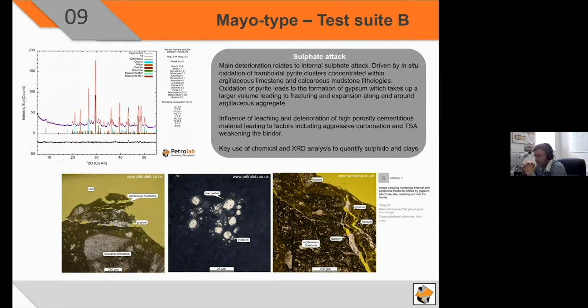In these samples, we've often found the influence of leaching and deterioration of the highly porous cementitious material can lead to aggressive forms of carbonation and, in severe cases, thaumasite attack, weakening the binder further. Within County Mayo or pyrite type investigations, the key use of chemical and XRD analysis to quantify sulfides and clays is a key part of the investigation.